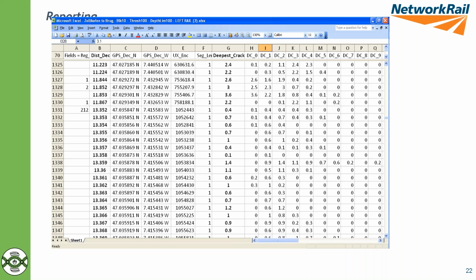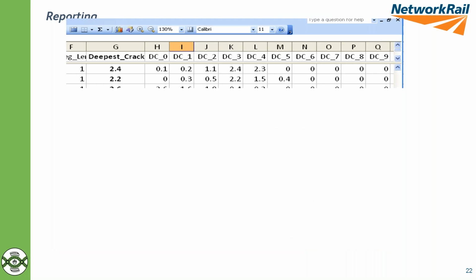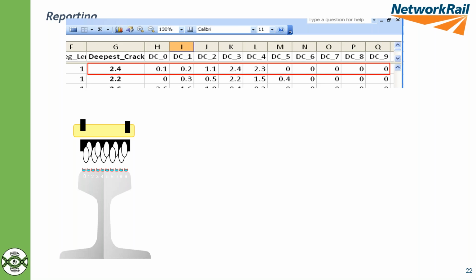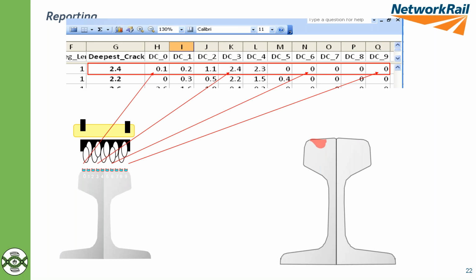And then under column G, you've got the deepest crack detected within that 1 yard. And as a bit of an example, the data in this situation, if you look at the top line of that data, you can see some cracking there under DC0, DC1, DC2. That corresponds to the probes which are mounted on the rail. So DC0 on the gauge side, DC9 on the field side. And if you correlate that to a transverse section through the rail, you can see the cracking there perhaps a bit deeper, but somewhere a region sort of 15 mil from the gauge corner, 20 mil at the deepest point.